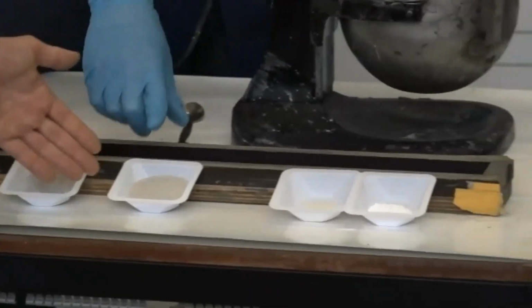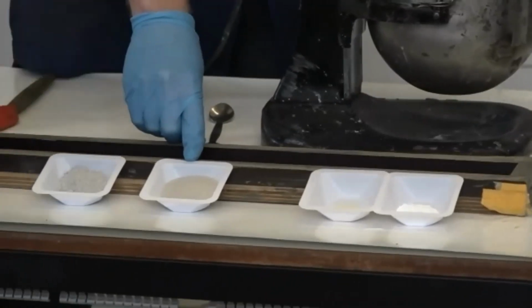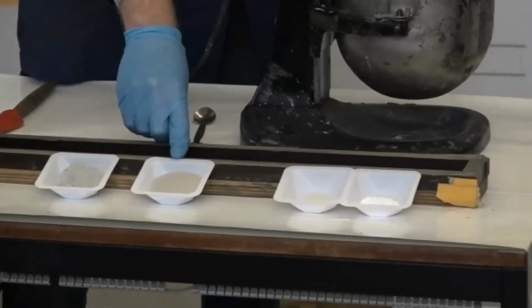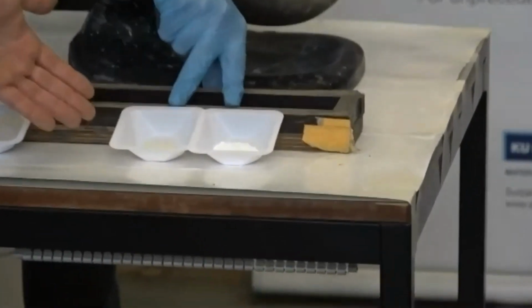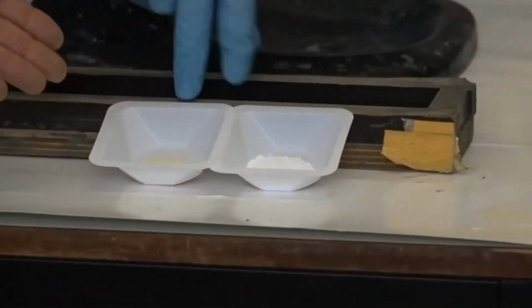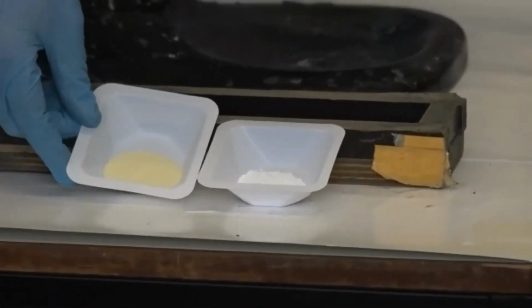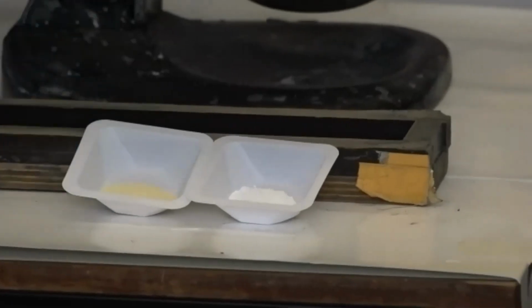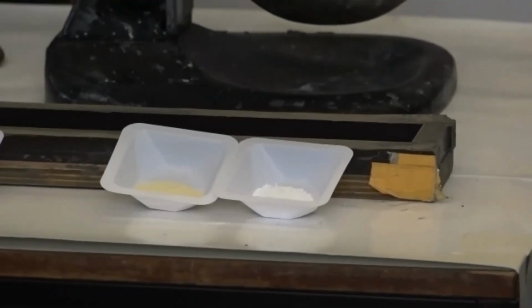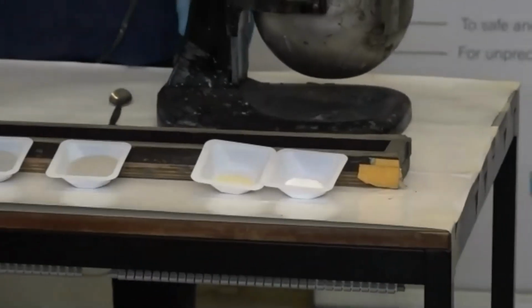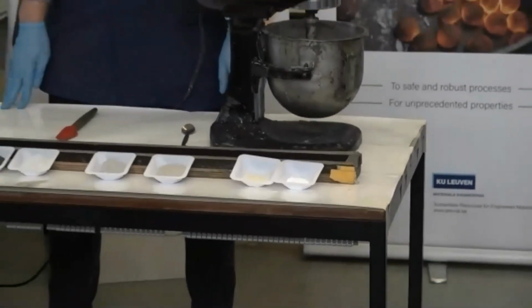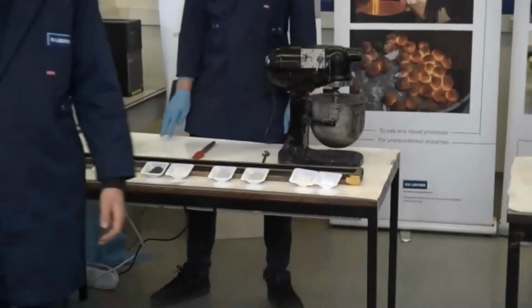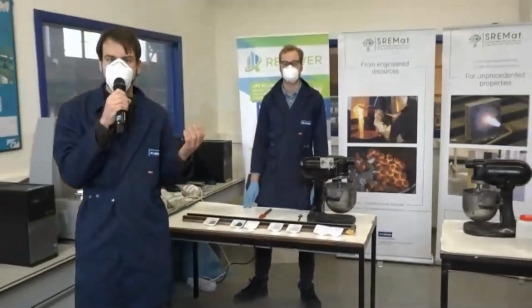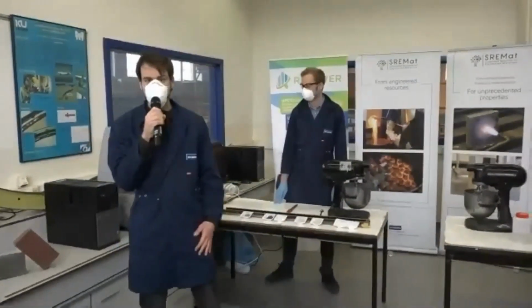Here you see, for instance, limestone, which we can add as a fine filler material. We can also add a coarser aggregate, which in this case is sand. And very important for these hybrid binders are additives. For instance, here you see in this yellow color, superplasticizer. The advantage of these hybrid binder systems is that we can use additives that also work in cement systems. That is the biggest advantage of these hybrid binders compared to inorganic polymers. And Michiel will now show you how to produce one of these hybrid binders.